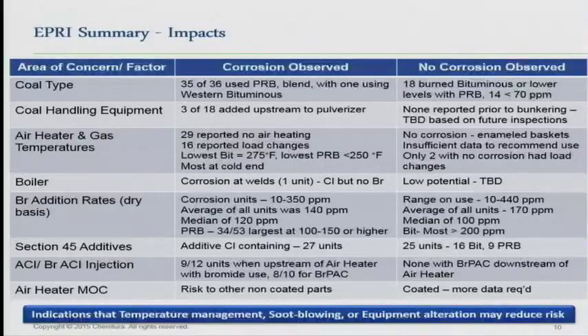So on the bromine addition rates, on a dry basis, they did the measurement here. The units that showed corrosion were anywhere from 10 to 350 parts per million of addition. When you look where there was no corrosion, the range was 10 to 440 parts per million. Okay, what's the big difference there? Again, one of the differences is the type of coal that was being burned. And then when you look at the average of the use, it is fairly similar. The median, not too much different.